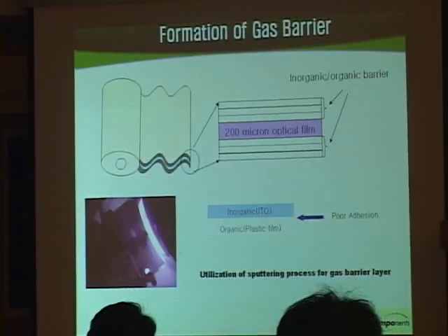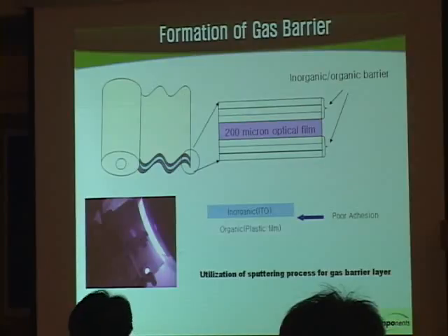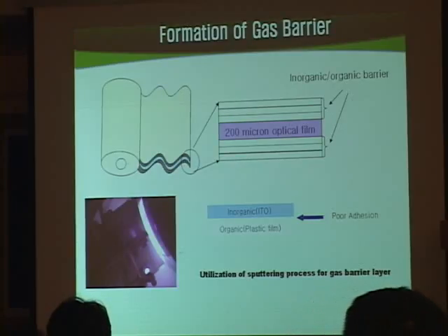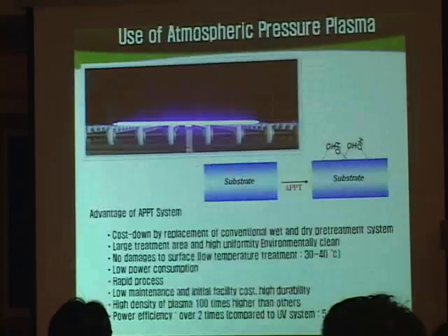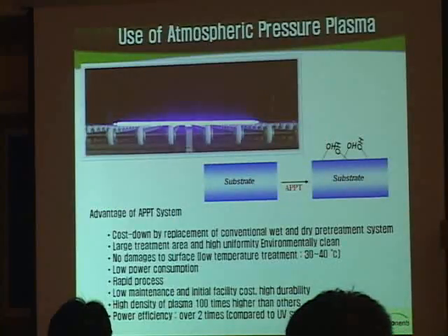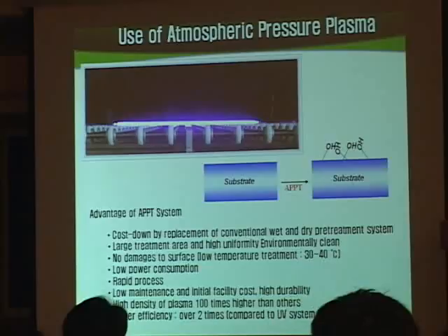They could make certain displays. However, eventually the failure comes in this kind of interfaces. It can be the interface between organic and inorganic of our substrate, or it can be the interface between our substrate and then other TFTs or some other things that the display manufacturer will put on. So what we try to utilize is atmospheric pressure plasma. In the display industry, atmospheric pressure plasma is starting to get certain attention for etching. But for us, etching is not of interest, because we do not want to damage our plastic film coating.